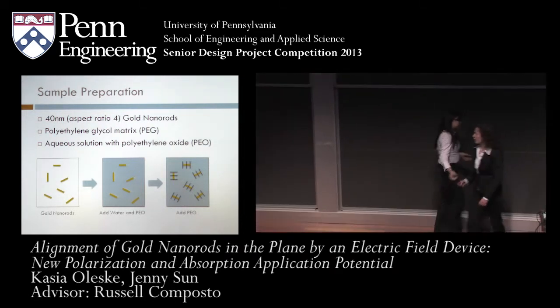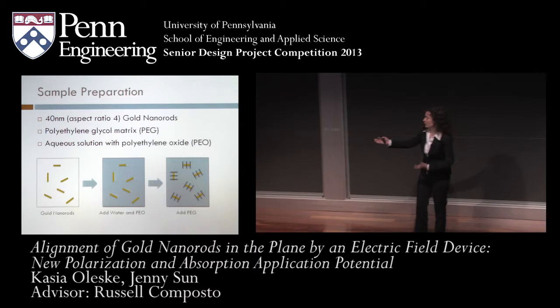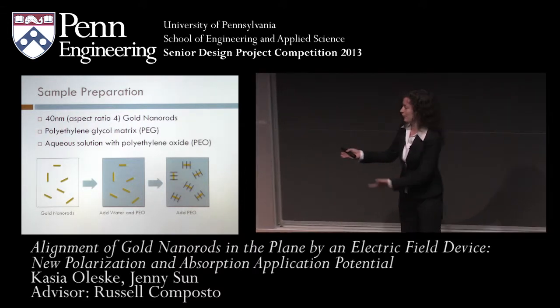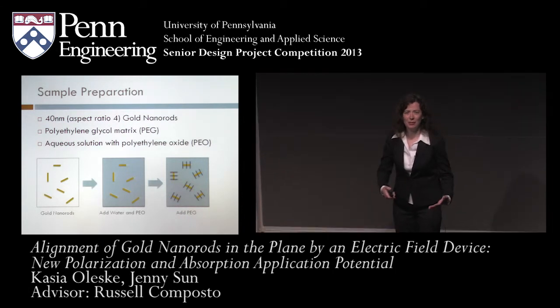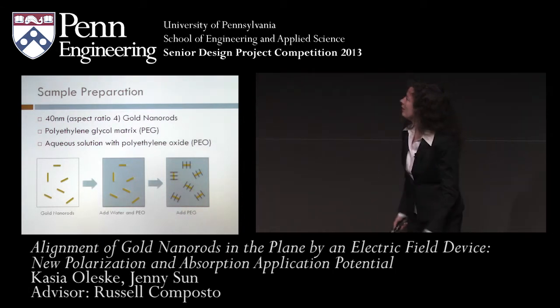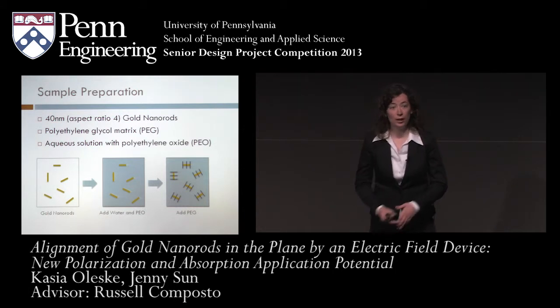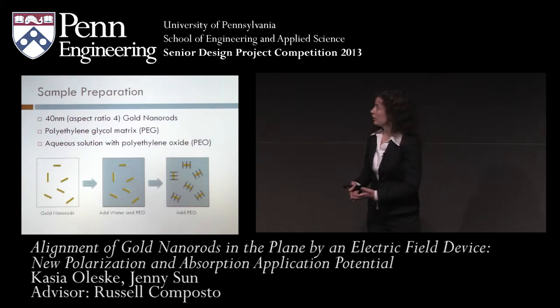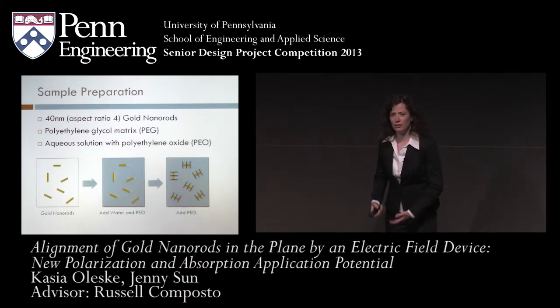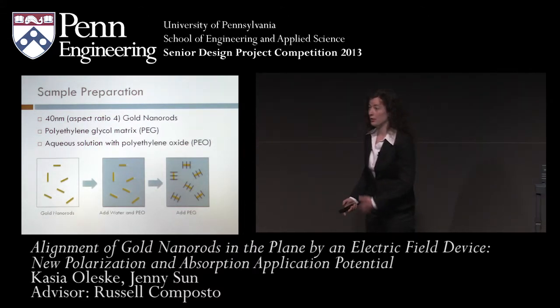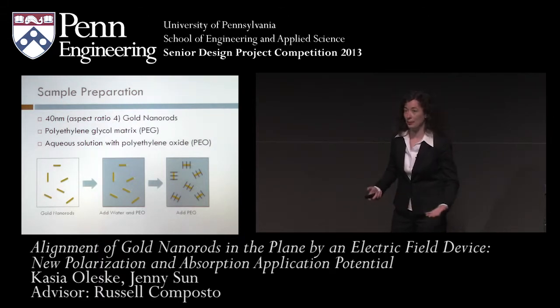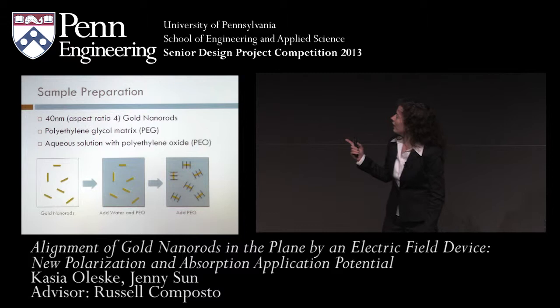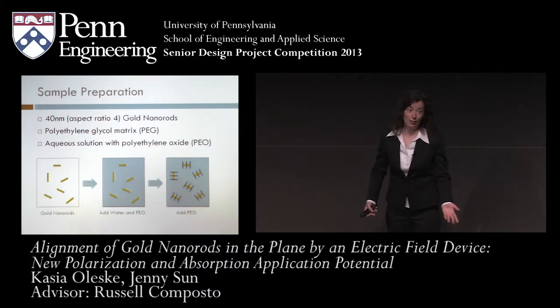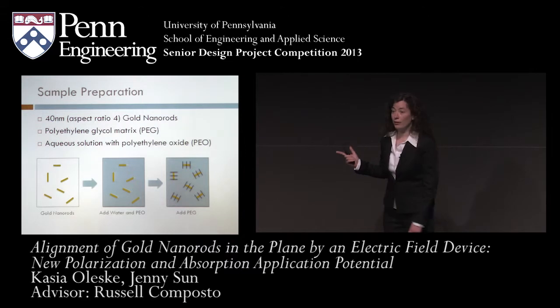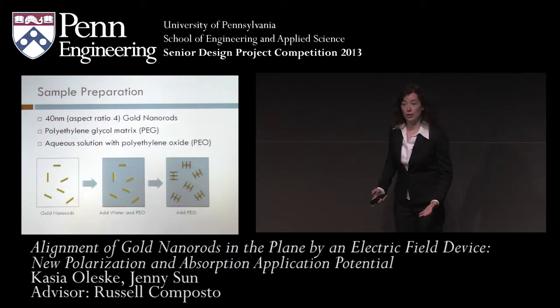Thanks, Jenny. So now that we have this electric field device, as you can see our final prototype over here to the left, it's time to start making samples and see, hey, what can this device do? So the system we wanted to test were gold nanorods in a PEG matrix. So the first step was acquiring these gold nanorods. So we got gold nanorods from the Murray group, which is a group in material science and engineering here at Penn. And then we put them into an aqueous solution, which basically means we added water as a solvent. And we added polyethylene oxide in order to lower the surface energy and make sure that the particles didn't conglomerate.